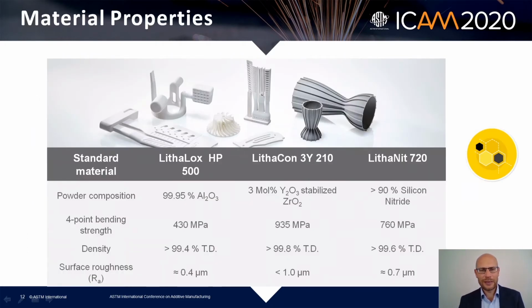Here you see as well some other ceramics which are also very common, alumina or zirconia. You see that the strengths and the densities are very comparable to conventional forming, and also, just as a matter of fact, the surface roughness, as you also saw in the silicon infiltrated silicon carbide part, they are very smooth, and all the parts which you have seen here so far have not been polished or ground. So this is the normal way of what we can achieve with our technology.